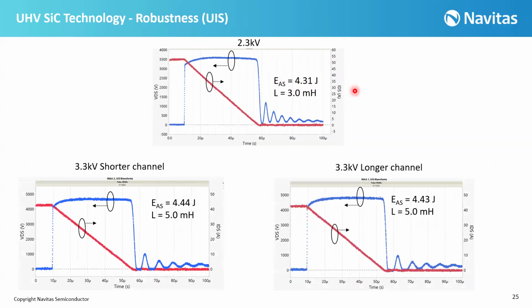Now if you look at the UIS capabilities for both the shorter channel and longer channel in 3.3 kilovolts, you can see the same capability for both of them, with avalanche energy of 4.44 and 4.43 joule, so the difference is negligible. We have the same capabilities with the same peak current and avalanche voltage. The voltage reached around 4.5 kilovolts, and the current reached around 44 to 45 amps. So obviously we can say that these 2.3 kilovolt devices and 3.3 kilovolt devices utilizing this technology are robust.